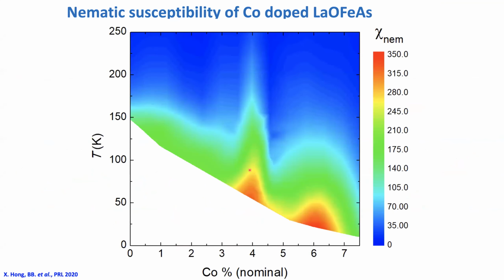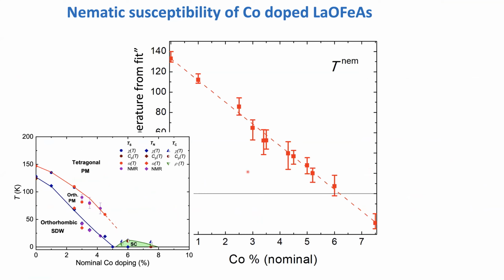I'm sorry, can I ask a question? Right. In the parent phase, you observe T nematic about 20 or 30 Kelvin below the actual transition, right? But it looks like from this phase diagram that they are actually at about the same temperature when they reach the quantum critical point. No? That's correct. You see, here 130 degrees is T_M, and the structural phase transition is at 150 degrees. But if you go to higher doping, T_nem approaches zero. In some sense, the separation temperature gets smaller and smaller as you approach the ordering temperature, and then of course I've shown you the data. This transition becomes extremely broad, and therefore I don't know what that means. Yeah, thank you.